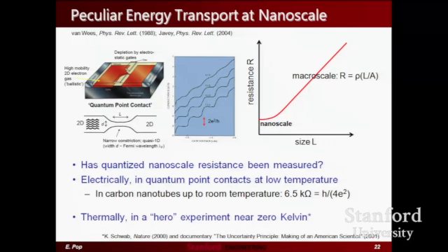And what's actually interesting is that both the electrical and the thermal resistance are expected to behave this way. So has this been measured? Well, it turns out that electrically, it had been measured since about the 1980s. Van Wees, 1988, had measured this in quantum point contacts at low temperature. I believe this was gallium arsenide. So this has been done. Even in carbon nanotubes, electrically, this has been measured all the way up to room temperature by work done by Professor Hongjie Dai here at Stanford back in 2004. Thermally, it was, to my knowledge, really only measured in a hero experiment done near 0 Kelvin, not particularly useful for everyday applications.